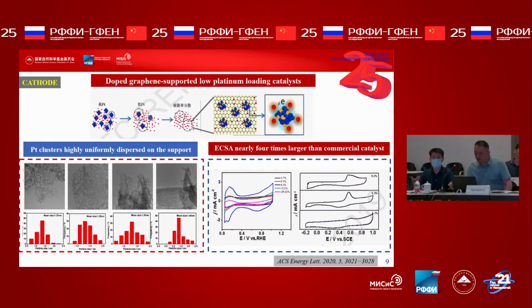The high resolution TEM images show that the platinum clusters prepared by this route have a small particle size and are uniformly dispersed on the support. And the electroactive area shows that the ECSA is nearly 4 times that of the commercial catalyst.